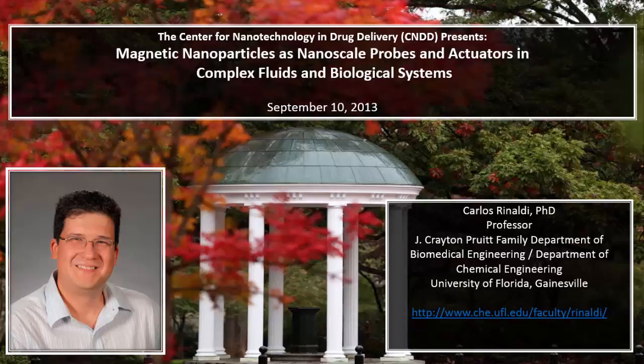There's evidence of a divergence between the drag on a particle measured at the macro scale and the nanoscale. The idea behind this is a breakdown of the so-called Stokes-Einstein equation for the diffusivity of a particle. And some of the early reports are from not too far away. This is from the University of South Carolina, where they were looking at rotational diffusion of anthracene in polymer melts. This is polyisobutylene, polyethylene, and polydimethylsiloxane.